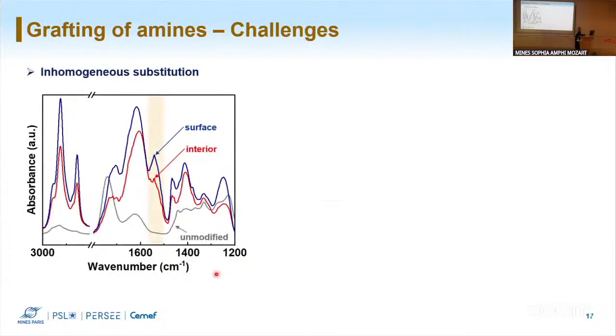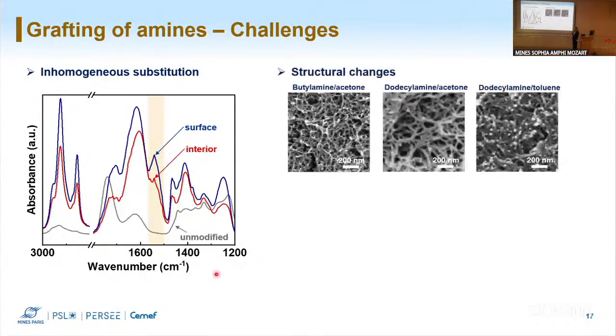However, we had a lot of challenges with this work, which is good and bad. So first we noticed that the substitution was not homogeneous. This we saw with FTIR. So we had a higher substitution on the surface of our aerogel and lower as we were going inside the material. Then we saw that we had some structural changes at the end. So we expected to obtain the same structure at the end since we had performed already the coagulation of our material, but we saw that during the reaction our gel was changing, and this was not always good for density and thermal conductivity.